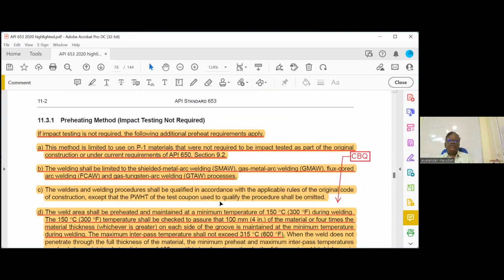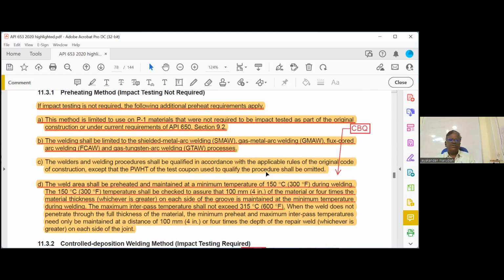Then this is the preheating method when impact testing is not required. Highlight this one. The method is limited to P1 materials that were not required to be impact tested as part of the original construction. The welding shall be limited to SMAW, FCAW, and GTAW. Then this is the only important one. The weld area shall be preheated to a minimum of 300 degrees Fahrenheit during welding. That is a closed book question.